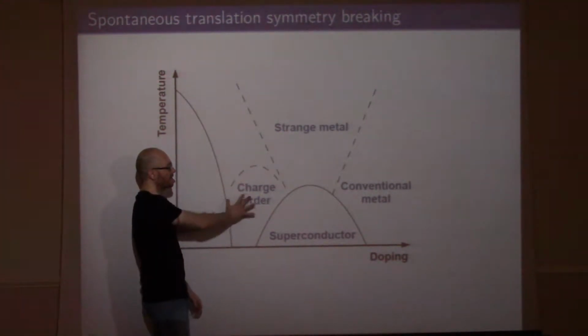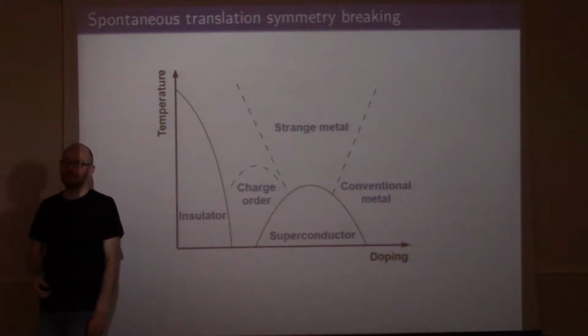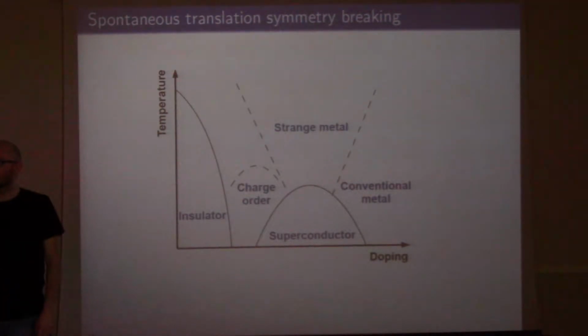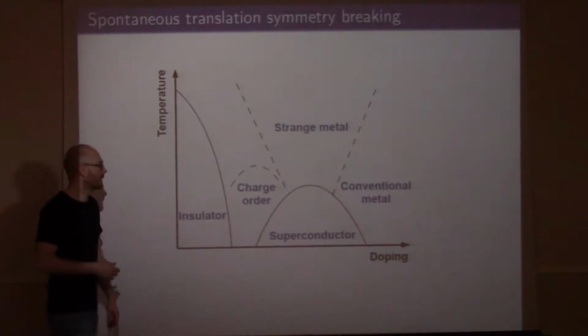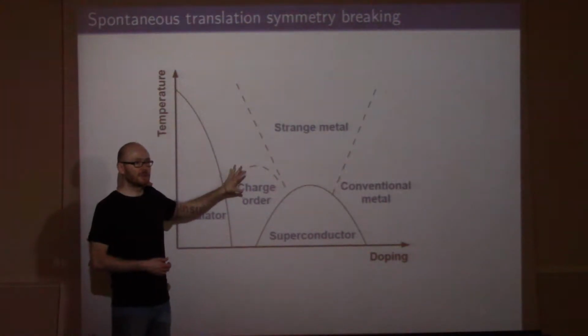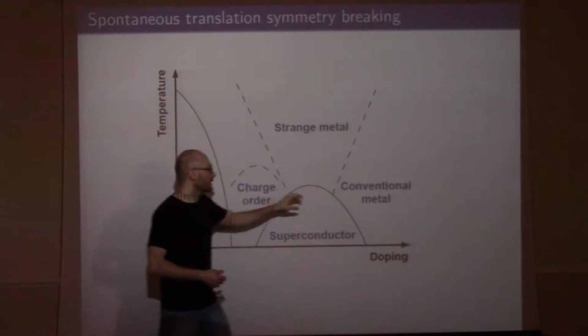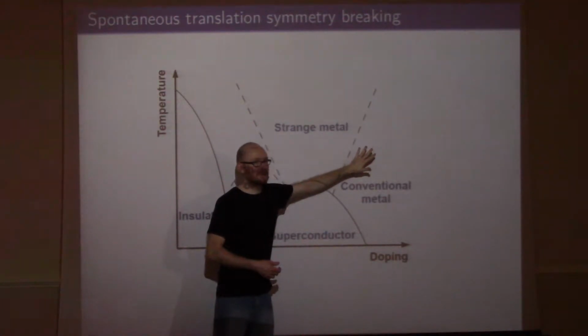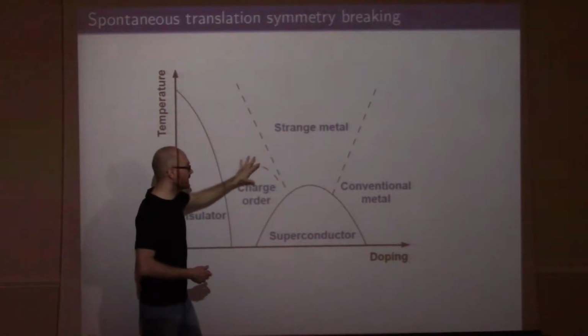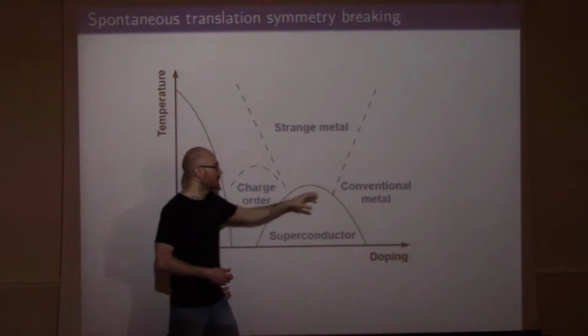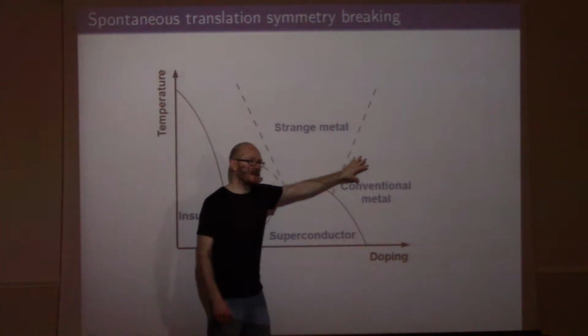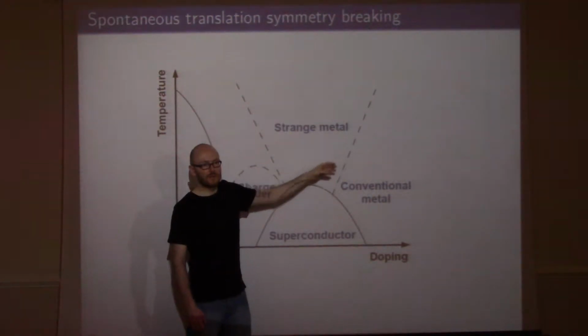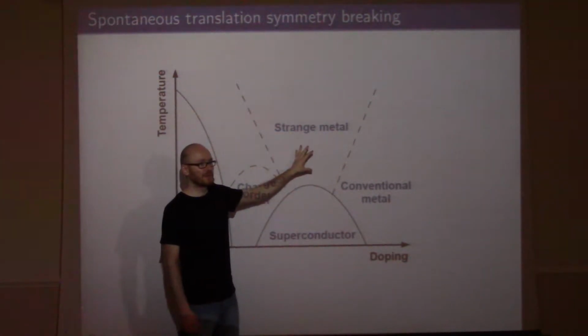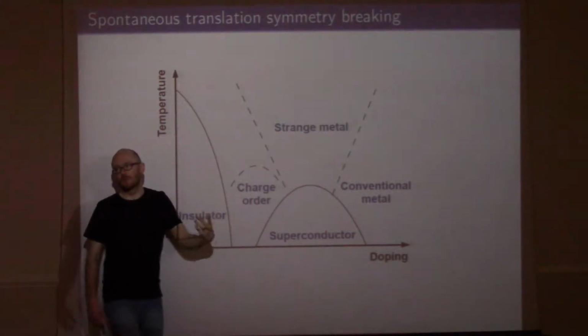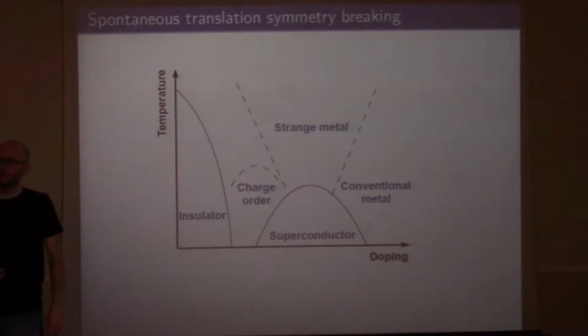And here people have detected lots of charge ordering phenomena, or at least periodicity. So it could be spin density waves, it could be charge density waves. So here there's a lot of spontaneous translation symmetry breaking. There are recent measurements that have detected them here. So it's kind of natural to think that if you have charge order here and some version of charge order there, then you could have some kind of fluctuating charge order also in this strange metallic region. So this is the logic of why we thought that it could be interesting to try to see what hydrodynamics has to say about charge density wave transport.